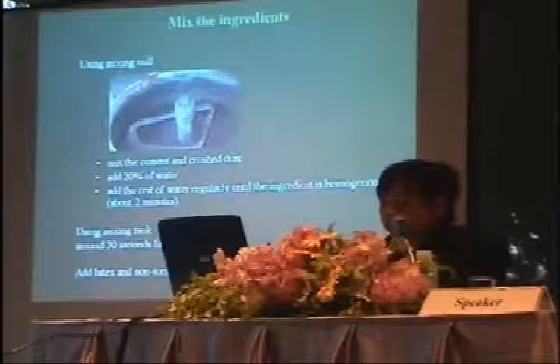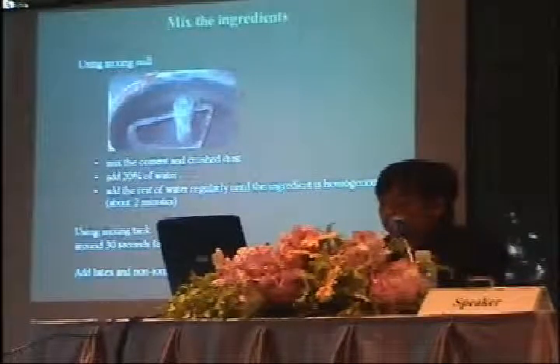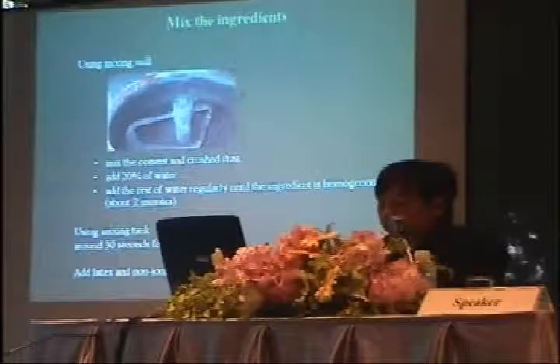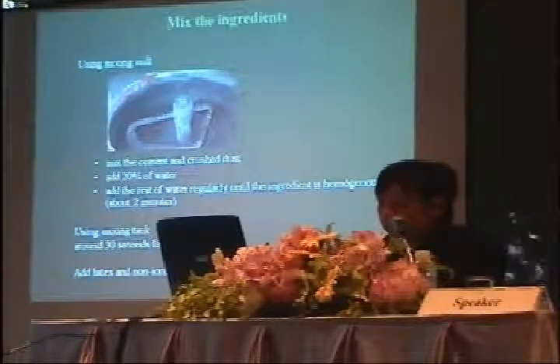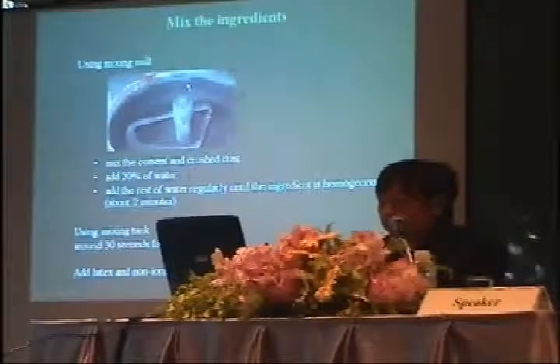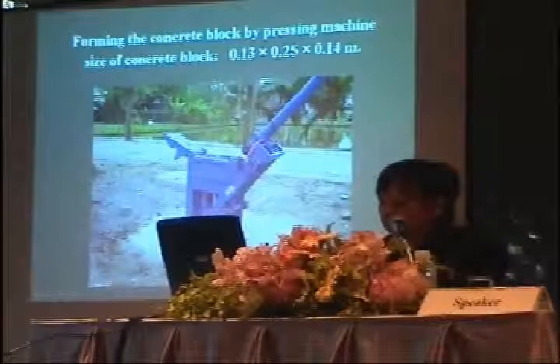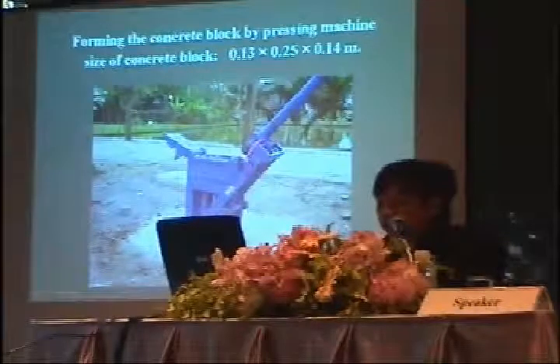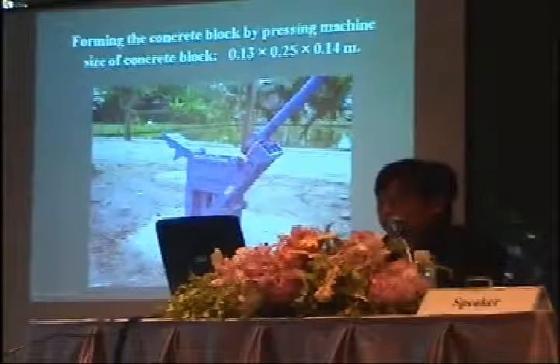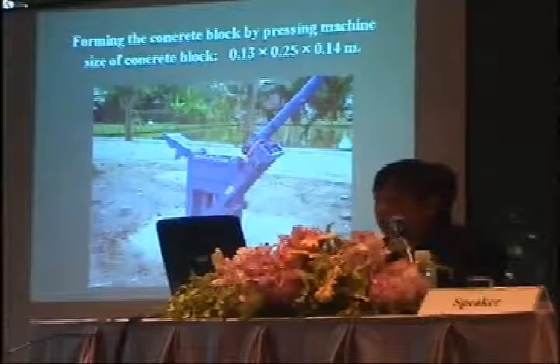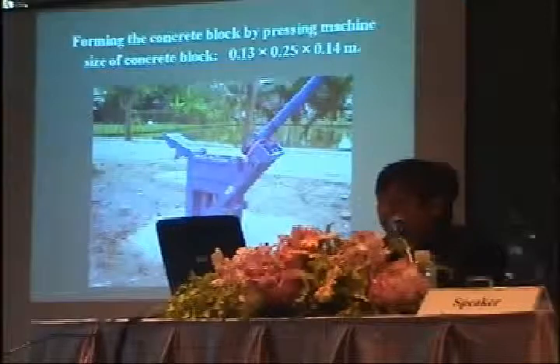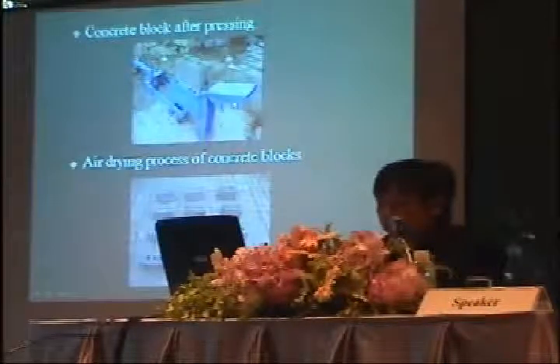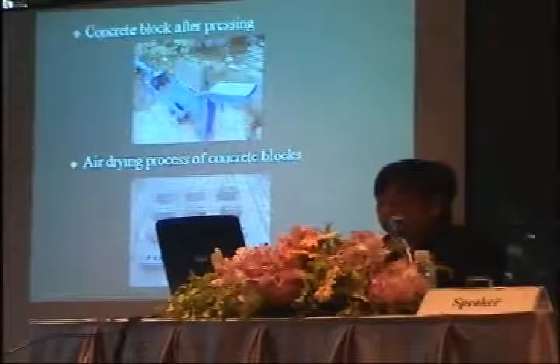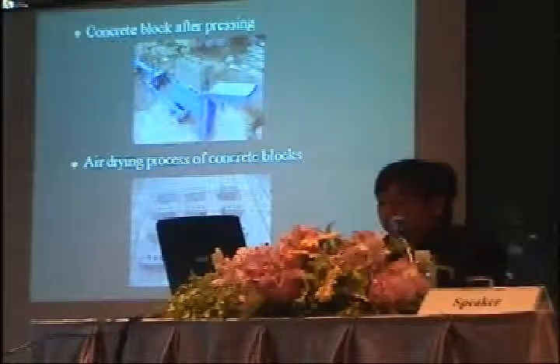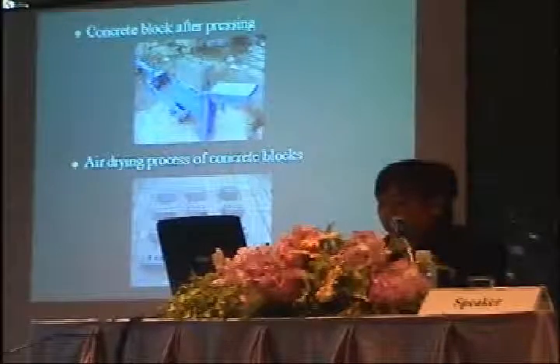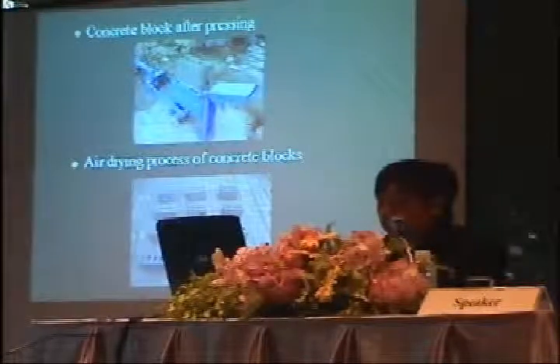Cement and crushed slag were mixed in a mixing mill. 20% of tap water was added and mixed for 2 minutes. Then add the latex and non-ionic surfactant. And the mix was molded by a pressing machine which used a lever arm, shown in the picture. The concrete block was then dried. The product is suitable for use and not different from conventional concrete block.